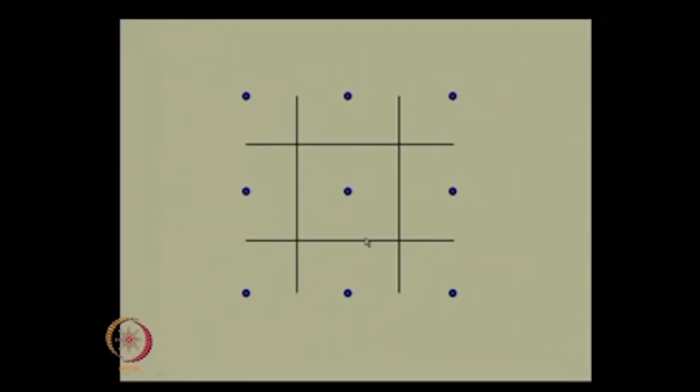In this situation, the nearest neighbors are these 1, 2, 3 and 4. With respect to these nearest neighbors we can draw vectors to them and then draw perpendicular bisectors to those vectors. A perpendicular bisector would appear here, there and here. So these are lines that perpendicularly bisect the vectors joining the origin to all its immediately neighboring lattice points. That is one set of such bisectors.